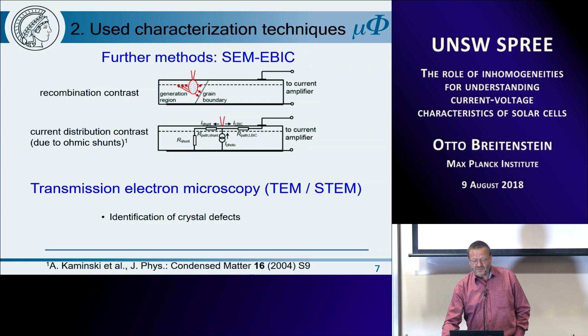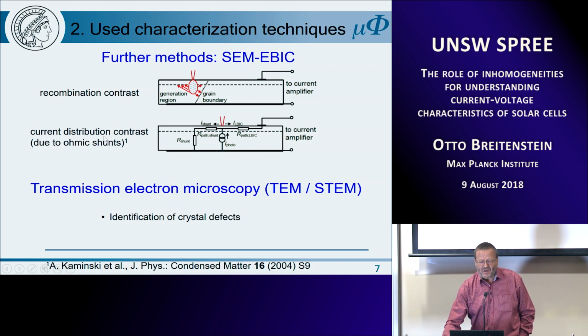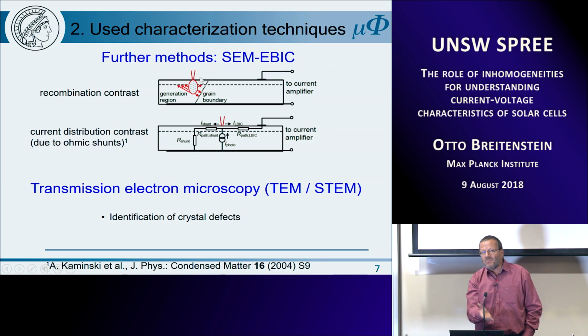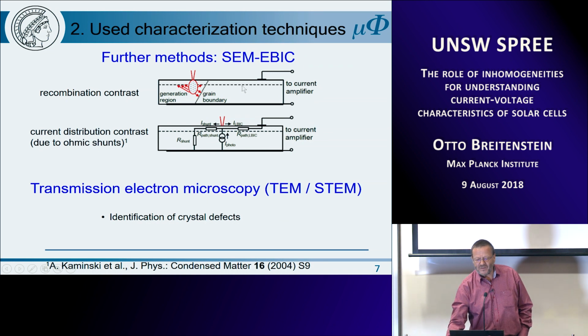And I have to remind you, if we have ohmic shunts, then we don't have the usual recombination contrast, which is sketched here. If we have a grain boundary, for example, we see it dark because part of the generated excess carriers are recombining before they flow back.